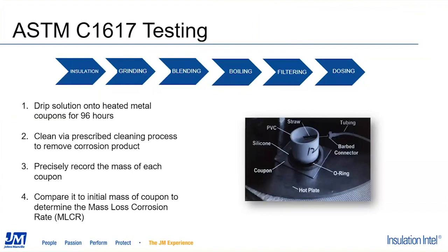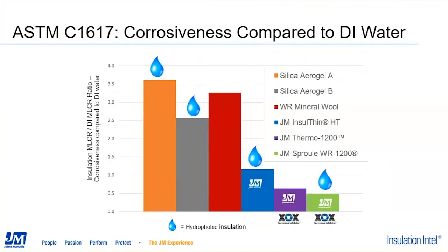Prior to subjecting the coupon to this test process, the weight or mass of the coupon is measured. At the completion of the 96-hour process, the coupon is measured again, and the difference between the initial and the final mass of the coupon is then used to calculate a mass loss corrosion rate, or MLCR, for each insulation material. So let's take a look at some of the results that have been developed using this ASTM C1617 method for evaluating the impact the materials will have.